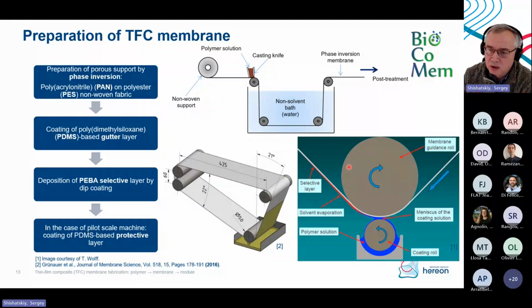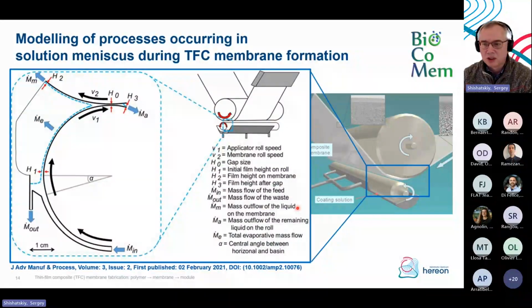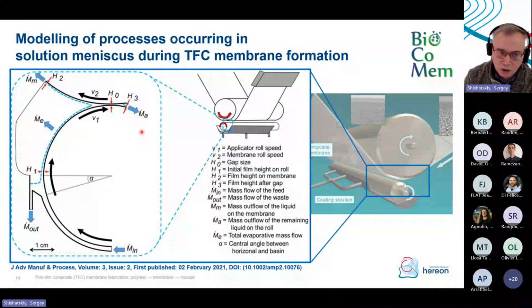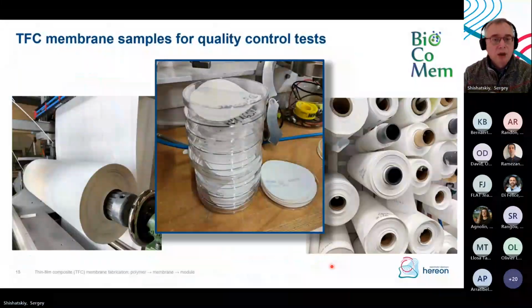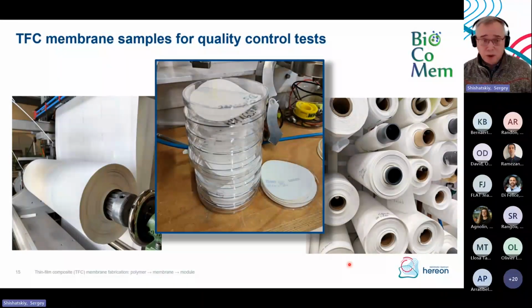rollers. One is just for guiding of the support. The second roller is for picking up polymer solution from the bath and bringing it into the meniscus. And we are actually pulling the polymer solution selective layer out of this meniscus. The processes which are occurring in this meniscus are described by very complicated mathematics. I will not go into this. You can see it if you want in the publication of Florian Brennecke and Julia Klot, which was published in 2021. Then you finally get your membrane. It's a roll of approximately 250 meters.